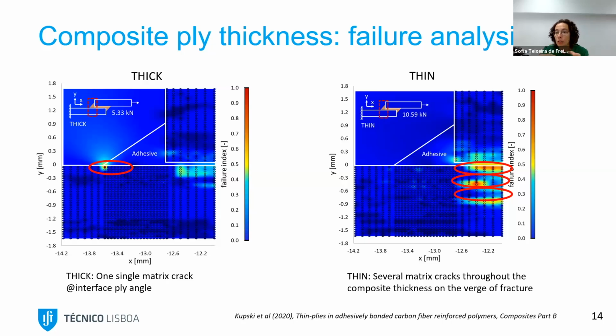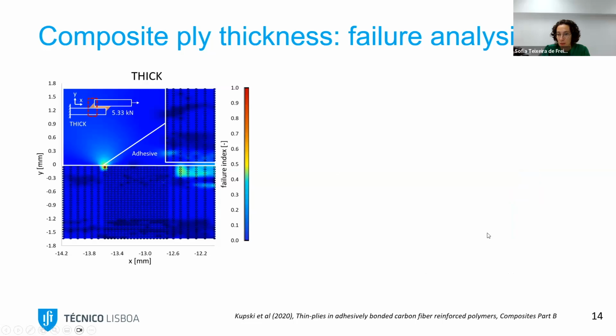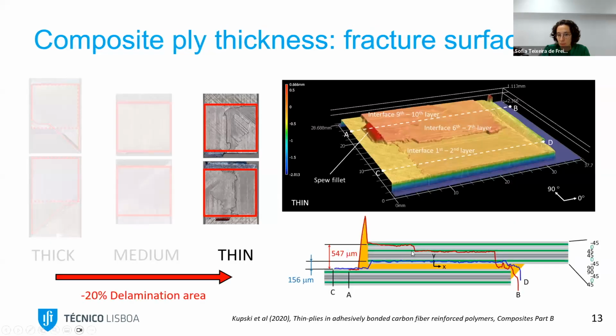So there is a crack competition between these different areas of the material. And because of this crack competition, once there is a crack, the cracks might be simultaneous or within a very close time frame, so they happen at the same time. And then they coalesce with each other. So this is why in the thin we see more steps in the fracture surface, as we saw here, because they happen at different locations and then coalesce all together.